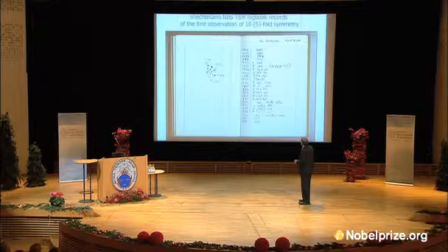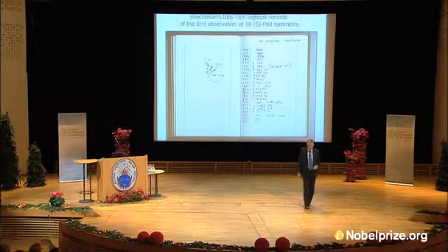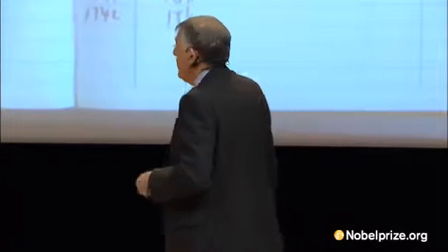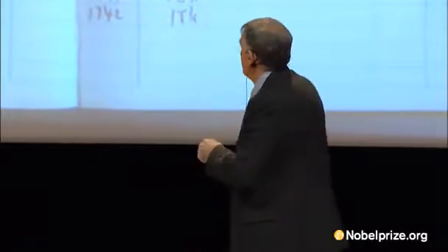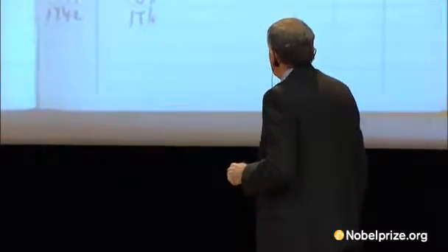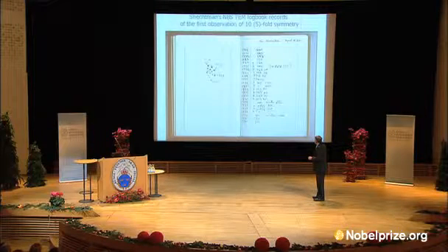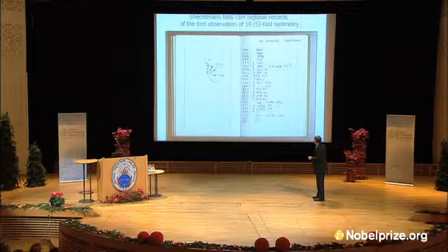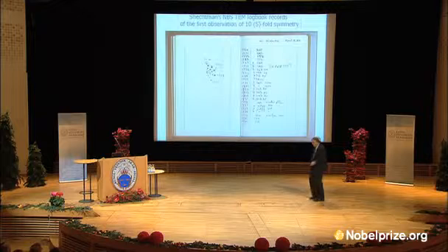So I started to perform a series of experiments. These are called dark field experiments in the transmission electron microscope, which were designed to find those twins. I didn't find them. So I performed another experiment called microdiffraction. See, all these three pictures are microdiffraction. Mu diff means microdiffraction.